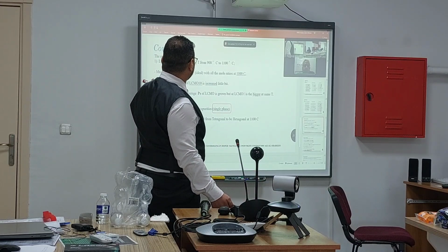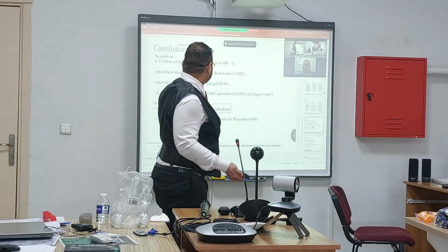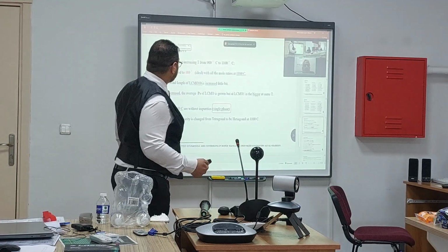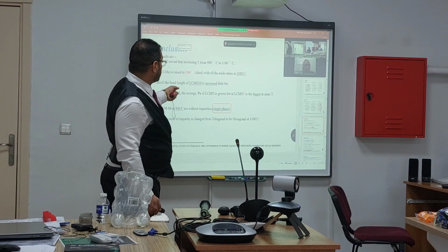Now it's a summary. Lanthanum calcium manganese oxide, in my opinion, was better, because when you increase the temperature, I have an ideal angle, 180, okay? At the same time, the manganese-oxygen bond length increased a little bit.